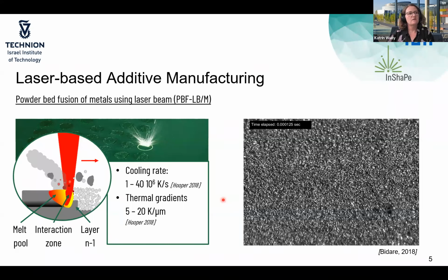What we have seen is that we increase the process window to come in the direction of a more stable processing. And what we can also see is that we change the microstructure and the solidification line. So this is the solidification line. This is the material which was molten before. And what you can see with the ring-shaped beam profile is that you change the microstructure and the solidification. But to understand this mechanism, we need to understand the temperature and temperature distribution during our processing, because that's the main thing we change: the thermal energy input with this Gaussian beam profile and the ring-shaped beam profile.